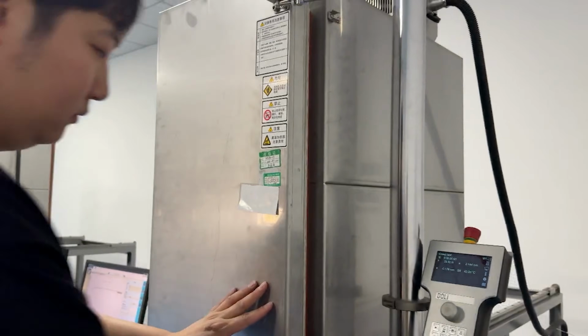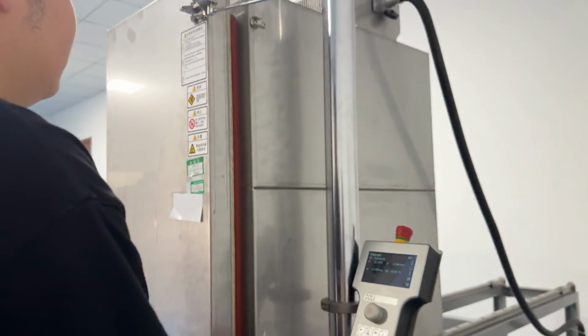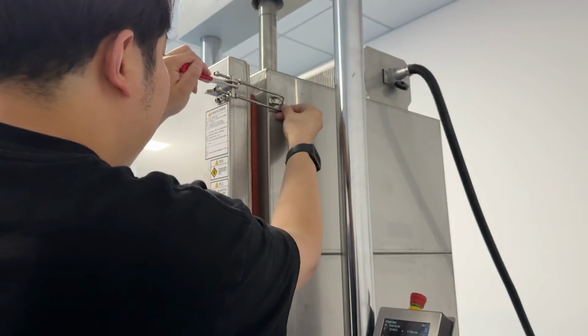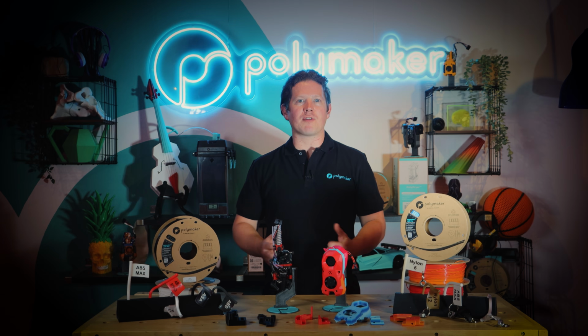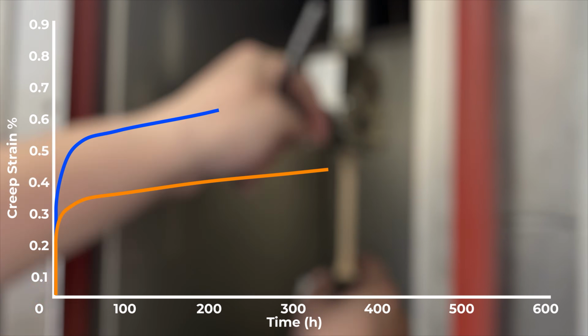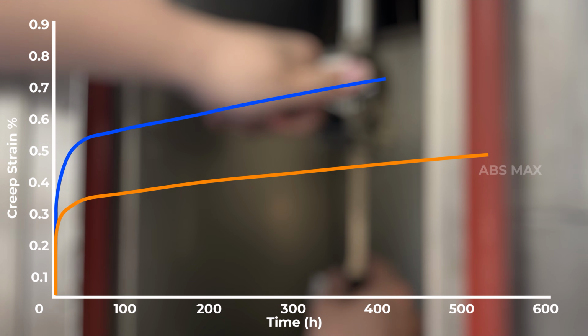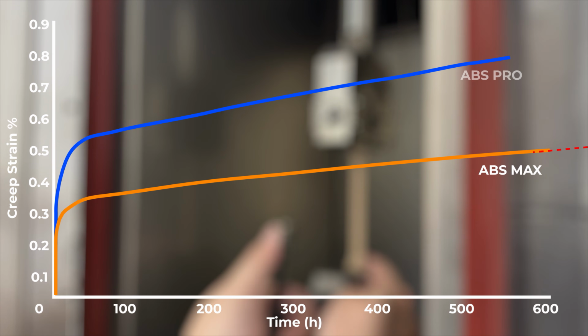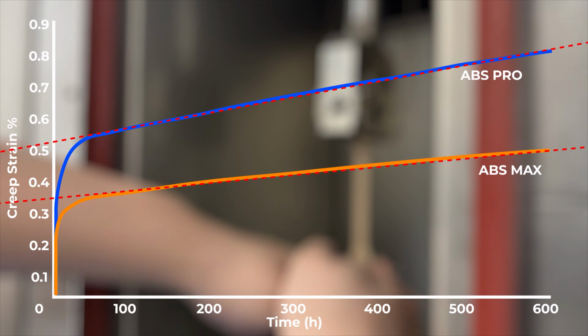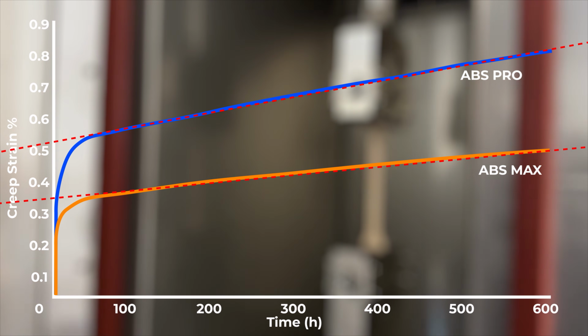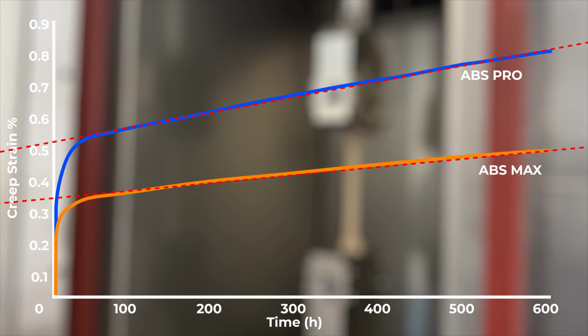We ran tests using 3D printed samples for 600 hours inside a temperature-controlled tensile tester. If we look at the graph, both materials display a linear path around the 50-hour mark, but where ABS Max really shines is the angle of this line as it diverges away from ABS Pro. After 600 hours of testing, the ABS Max sample shows a creep strain of just 0.5%, with ABS Pro at 0.8%.